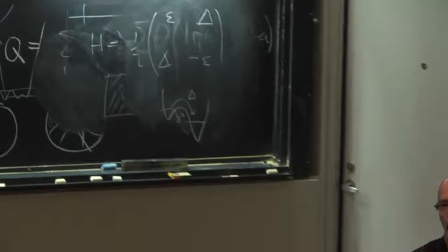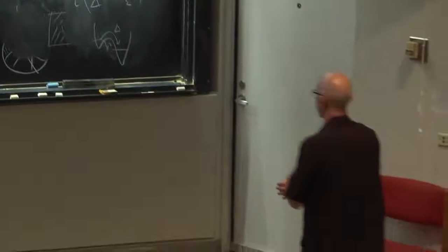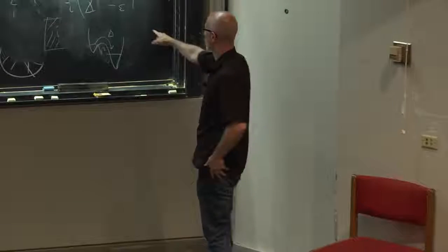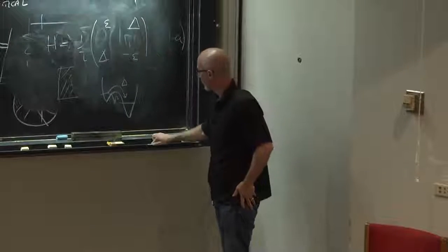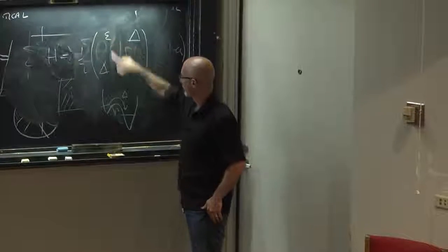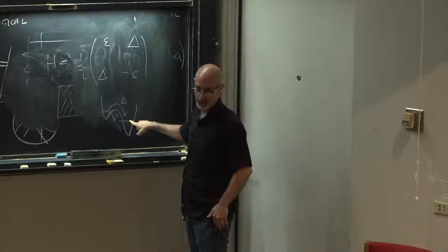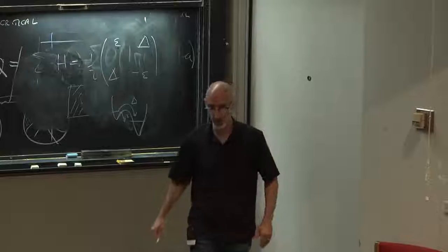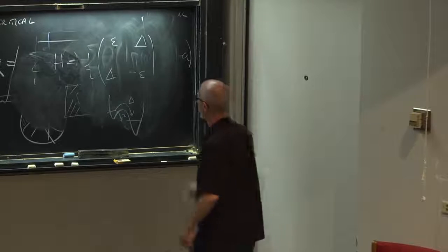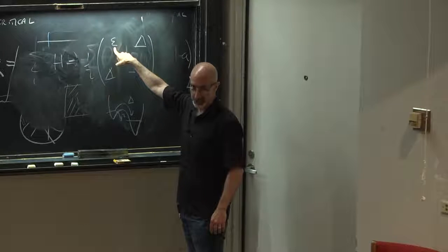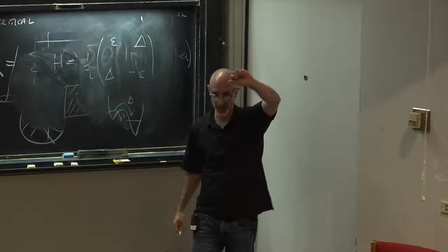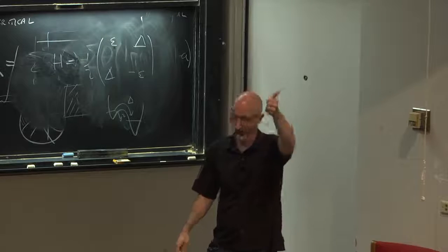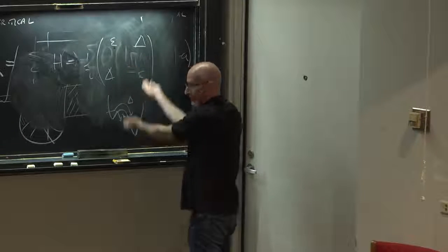Okay, so something like 1 in 10,000 per atom two-level systems will give rise to a behavior that if you had a distribution of these two-level systems, and basically what they said was the epsilon and the delta will not be correlated. The probability distribution of epsilon they'll take as flat, because it doesn't matter whether or not you have plus epsilon or minus epsilon. That just reverses this.